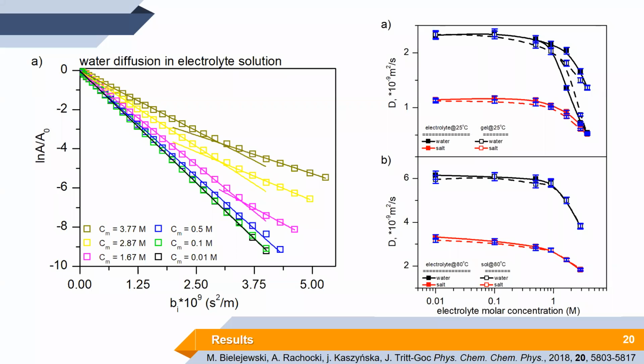To check this, we analyzed the data in the so-called Stejskal-Tanner presentation, which you see on the left side. And we noticed that for high concentrations of the ions, we observe two slopes. And in this presentation, such behavior stands for two different diffusion coefficients. If there were a distribution of diffusion coefficients, then we would observe a curvature in that presentation. Okay, so that's the one point.